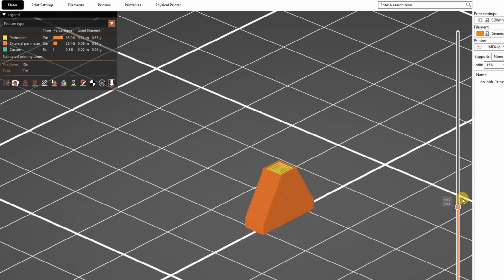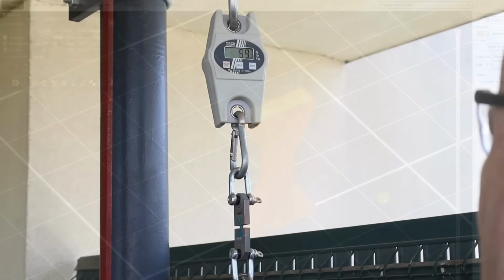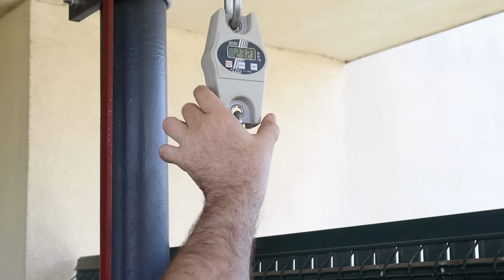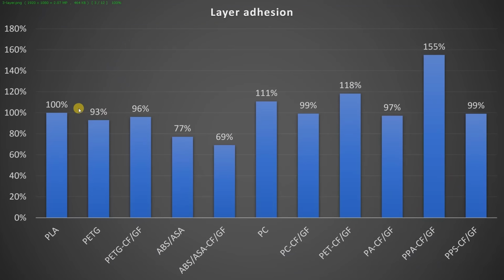Layer adhesion. The object is printed in vertical position and also the smallest cross-section area is 4x4 mm, and I'm measuring the break load. From basic materials, PLA is the strongest and by far the weakest is the ABS ASA. Usually the fiber reinforcement will make this layer adhesion weaker in most cases, except with the PETG. Looks like the company somehow solved that carbon or glass fiber reinforcement sticks well to the basic materials, and I could measure here some really good layer adhesion.